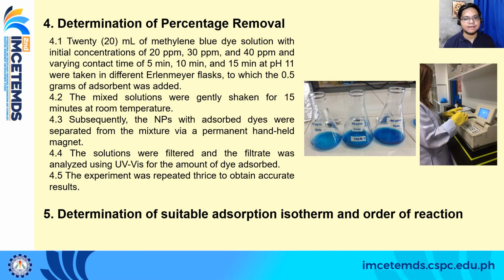We had two varying parameters here: the initial dye concentration, which are 20 ppm, 30 ppm, and 40 ppm. And for the contact time, that would be 5 minutes, 10 minutes, and 15 minutes. The controlled parameters here are the pH, which is at 11, and the amount of adsorbent used, which is at 0.5 grams. And also, the experiment was repeated thrice to obtain accurate results.